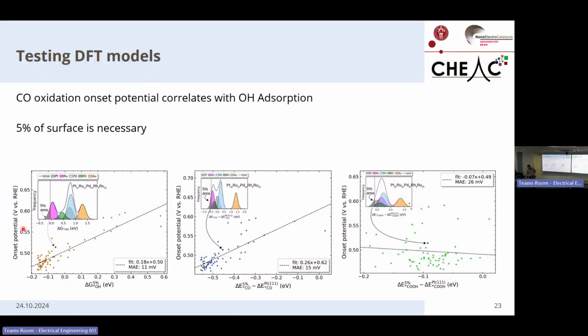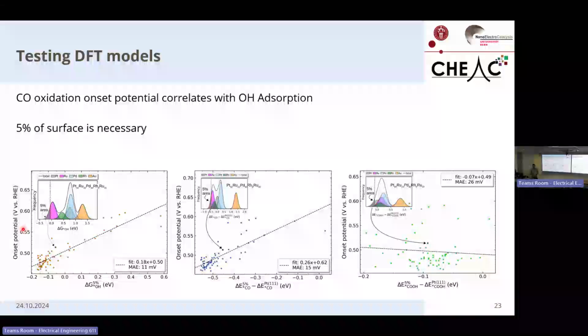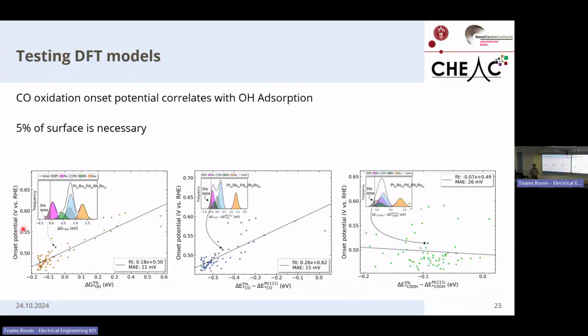In addition, in these DFT calculations, Jack was also varying the fraction of the surface that was considered in the calculations. And it turns out that you get the best correlation also if you take only the top 5% of the active sites into account. And that explains why our optimum is such a large domain. If you just need 5% of the active sites to be active for the CO oxidation, you don't need to add more ruthenium at some point because it will not increase the activity.